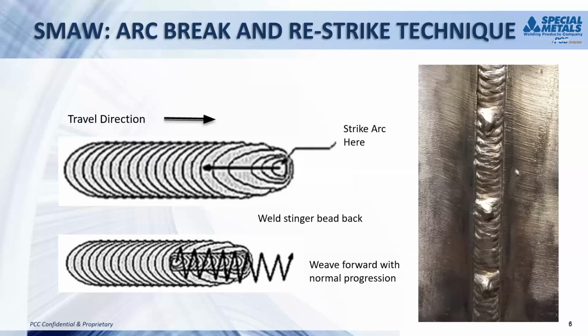What that does is a little bit different weave pattern where you're bringing that start up upon the previous bead. And that makes it very easy to grind off and then very easy to remove any potential porosity or any issues with that start. It's not always the prettiest pattern, so if you're not going to be machining the weld, or it's going to be left as is, you may want to take the risk and have that start going forward where you're actually welding over it. But if you are doing a lab plate or a qualification, it is a very good idea to pull that out, where you can eliminate any chance of start porosity. You can grind it off and remove it. Using that technique definitely helps passing x-rays and making your qualifications go a little bit smoother.